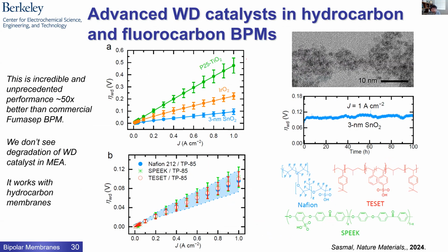So using this sort of design, we said we want really good electronic conductors. To get that, we probably want highly crystalline materials. In fact, whenever we try amorphous materials or MOFs, metal organic frameworks that have high surface areas, they're really terrible for dissociating water. So we realized that, from the literature really, and from trial and error: tin oxide. If you take SnCl4, it hydrolyzes at room temperature in liquid water to form crystalline tin oxide. You never have to heat it up.